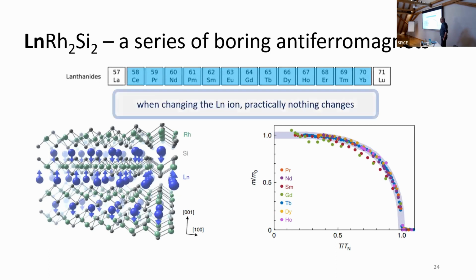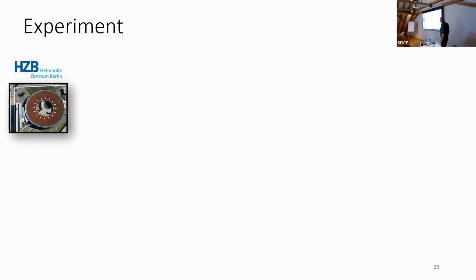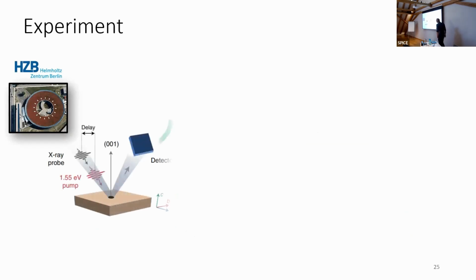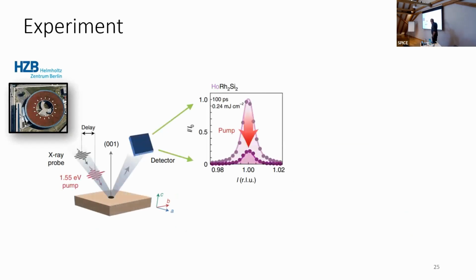This is very useful for us because we can essentially change the magnetic ion, effectively only changing the 4f filling, which is kind of remarkable. We found a system that's so boring we could actually do that. This is what our experiment looks like. Shine light in, shine light out, at femtoslicing at BESSY. We get a Bragg peak, we quench this Bragg peak, and we watch it go away as a function of delay.